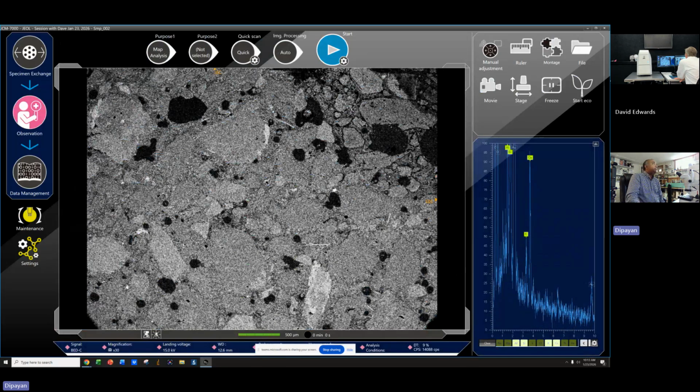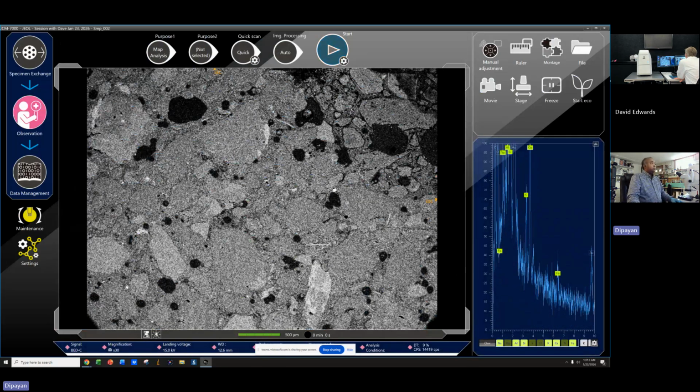Isn't that the one where the aggregate that came in had stuff that swells when it gets wet? Yeah, that's the pyrrhotite problem. That was very common in Connecticut. Now in Massachusetts, a lot of homes are affected. We're working on that, and all the quarries there are testing their stone, because now they won't approve the aggregate until it has passed for pyrrhotite. Right. So let's go back so we can handle that.